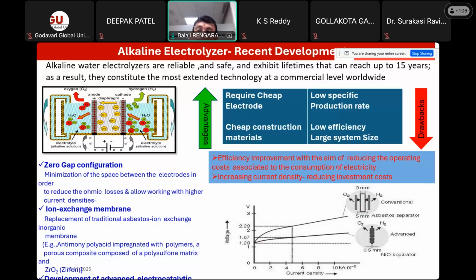The main drawback of this alkaline base, though it has the advantage of using non-noble metal based electrode material, is that the hydrogen production depends on the current which you are pumping into the electrochemical cell. But in the case of alkaline, you cannot pump more current, because the maximum current which you can pump based on the material you have chosen is 400 milliampere per centimeter square. So if you have a 1 centimeter square electrode area, you can go a maximum of 400 milliamps, and then the corresponding hydrogen can be produced from the electrode.